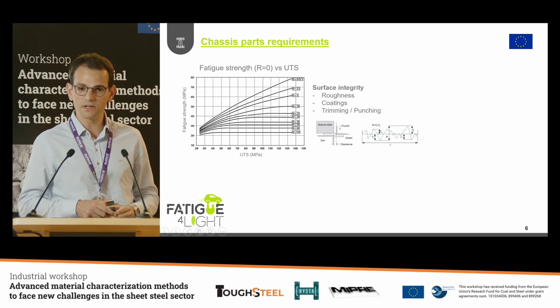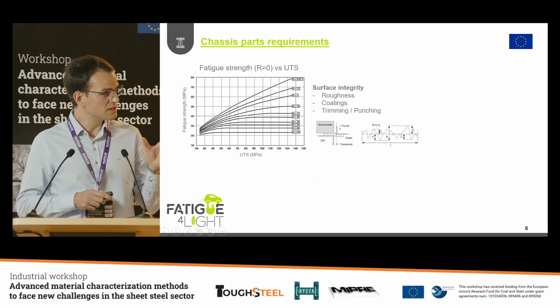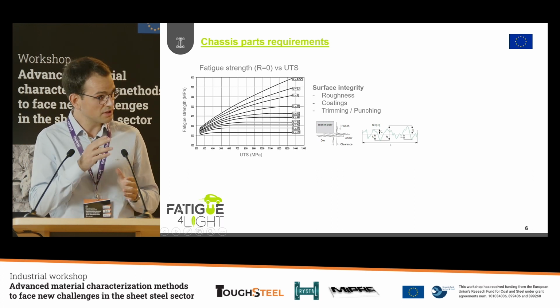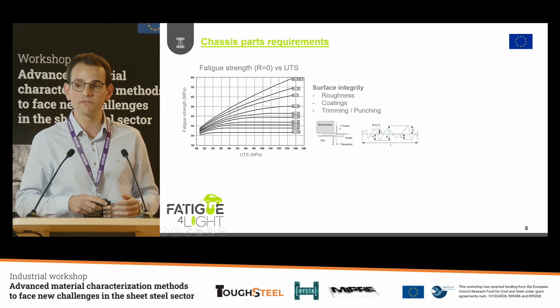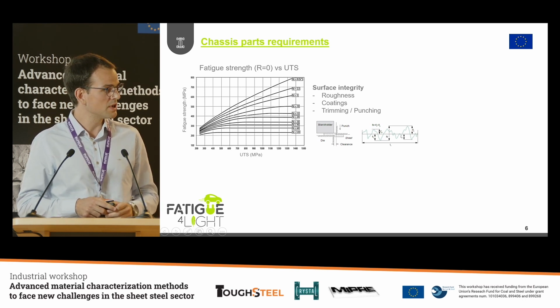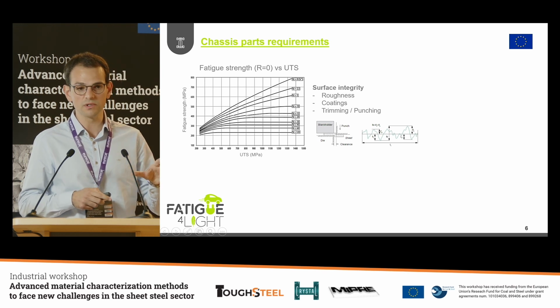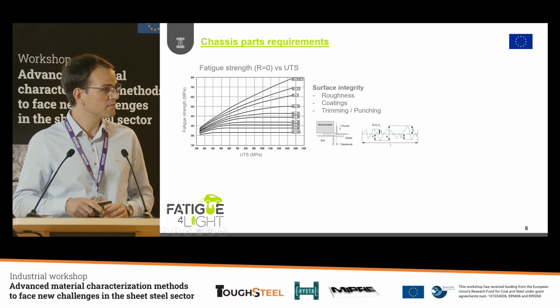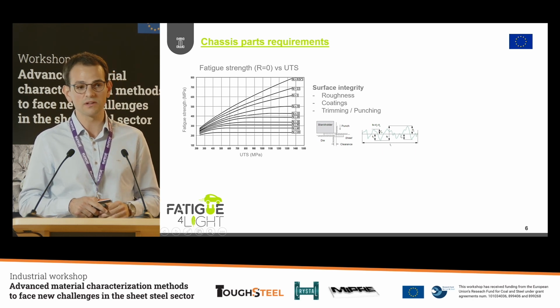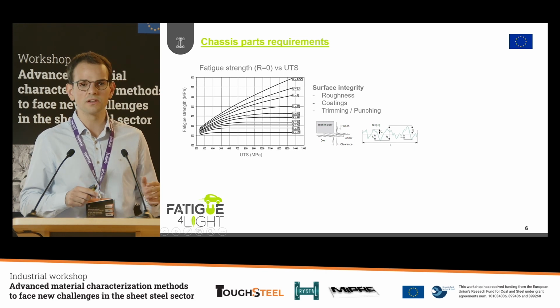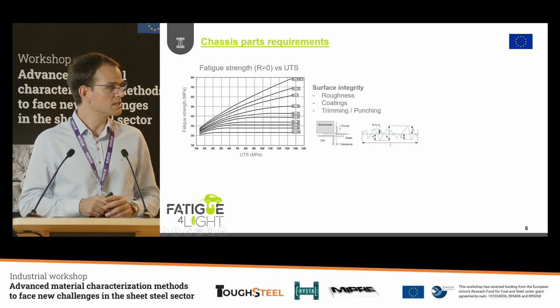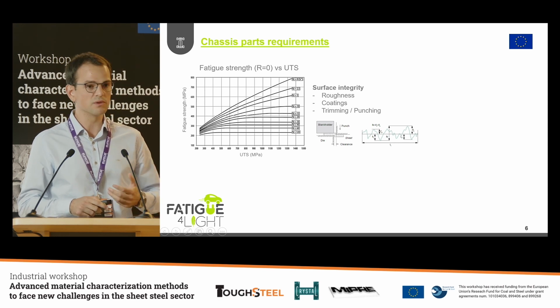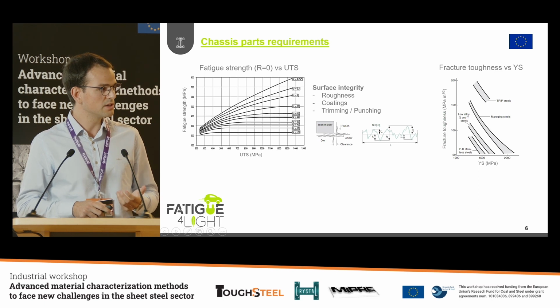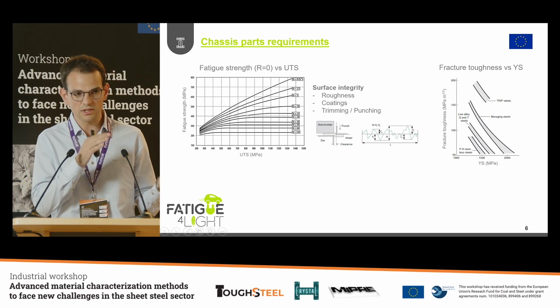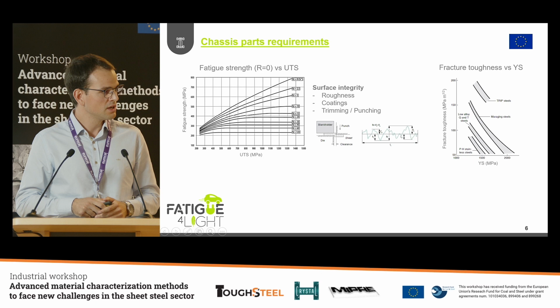But when we are addressing these different applications where we have trimming operations, serrated edges, or also perhaps we have some coatings like in press hardening materials, we are introducing some defects in the material. So such defects can reduce and limit the fatigue resistance of the material. Then it's not that clear that the lightweight design can be addressed by only using a material with a higher tensile strength. Additionally, if you look at the fracture toughness evolution by considering increasing the tensile strength, we see that